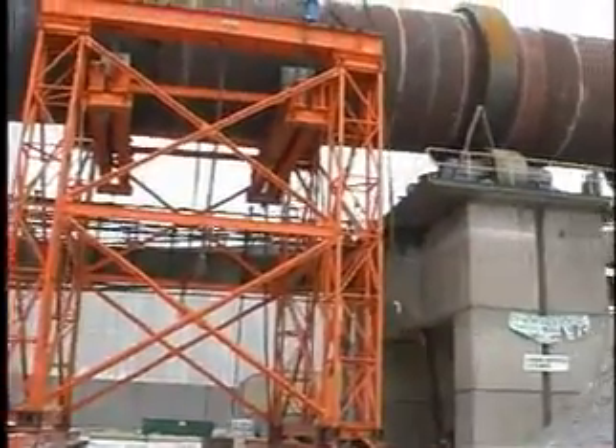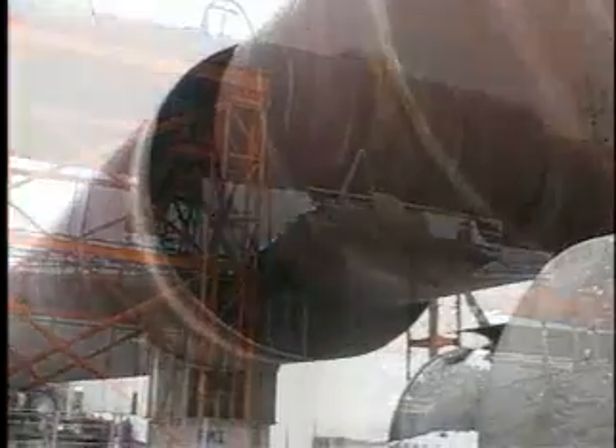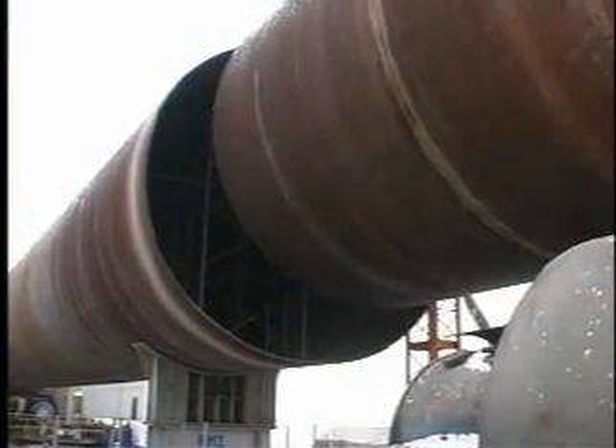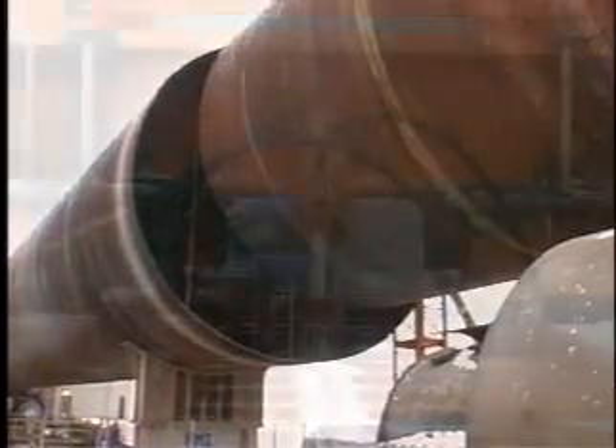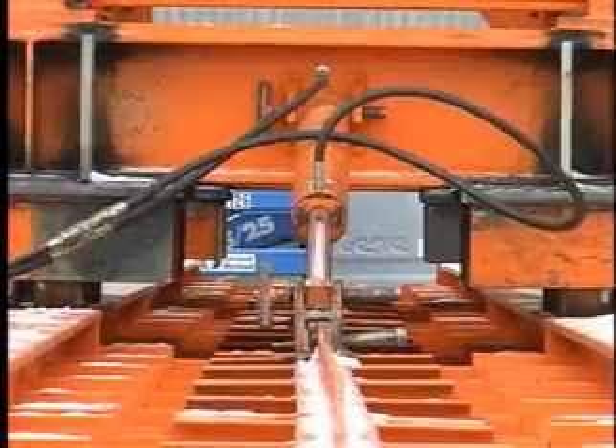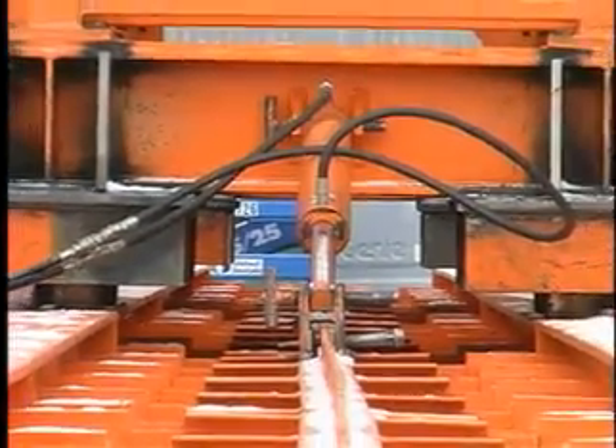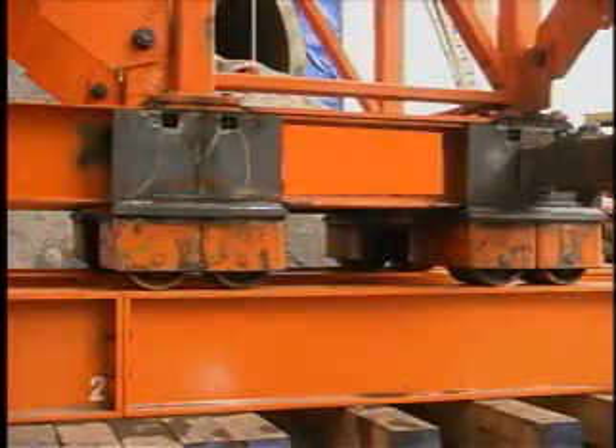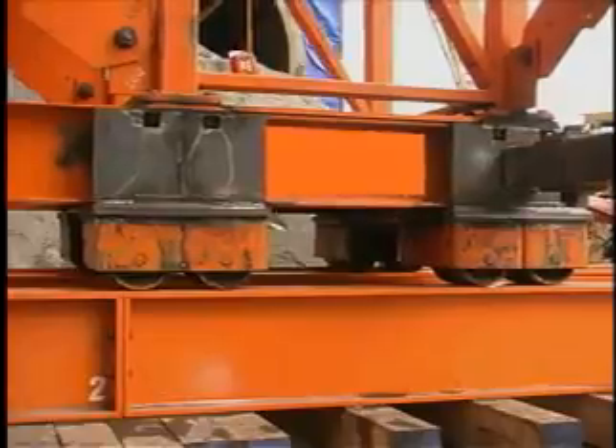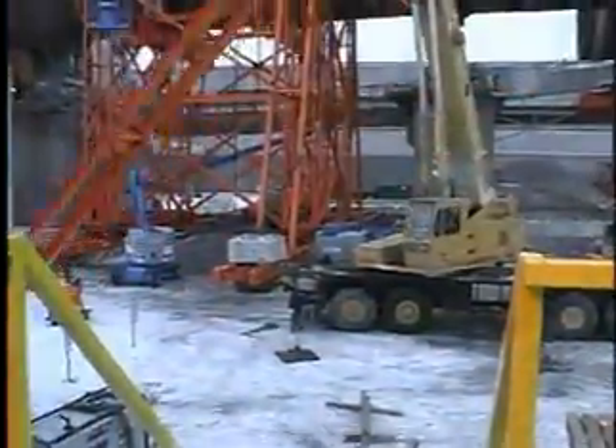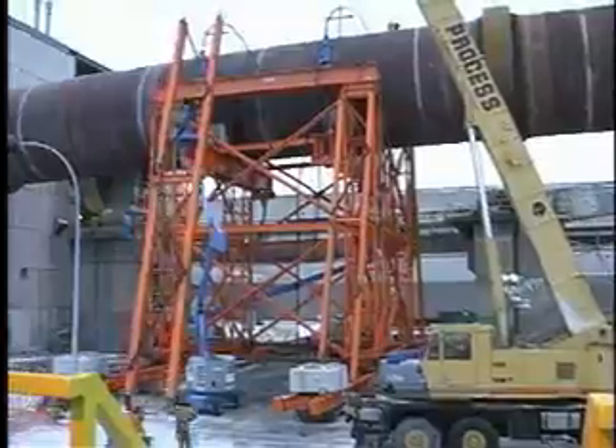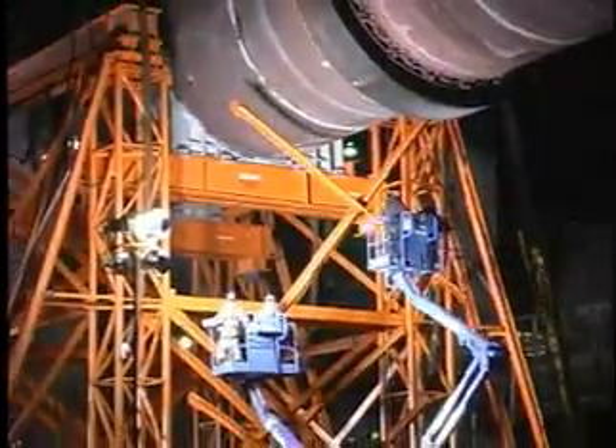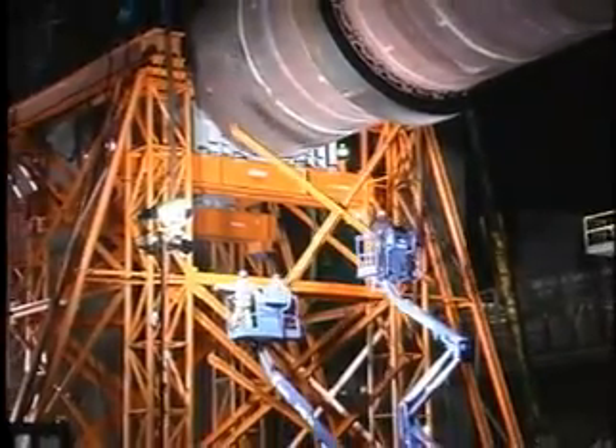The fully braced lifting tower and strand jack system then picked the 450-ton, 130-foot-long damaged kiln shell out of the rollers and was slowly propelled away by hydraulic jacks connected between the tower leg base rollers and the twin-track runway system. Once the 35-foot horizontal travel was achieved to clear the piers, external A-frame outriggers were installed on the tower legs to maintain stability, and the tower cross bracing was sequentially removed as the kiln was lowered to the ground for further demolition and removal from site.